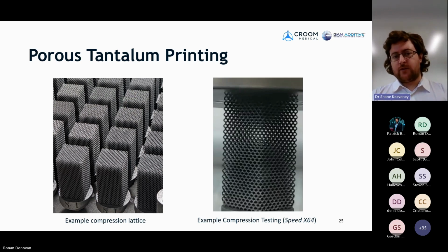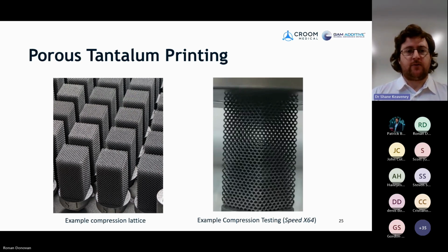Now, that on one side makes our parts heavier, which is one piece, but we'd aim this printing process more towards lightweighted porous structures. However, for the powder, it actually helps a great deal with the flowability of the powder and also the cleaning of the parts too. So with the heavier powder, obviously it's easier for gravity to work on it and clean these structures out. So we found cleaning to be good as well, and the flowability for coating as well, quite good for the powder. As I said, quite consistent results in terms of the overall geometry, quite a range of geometries, good control.